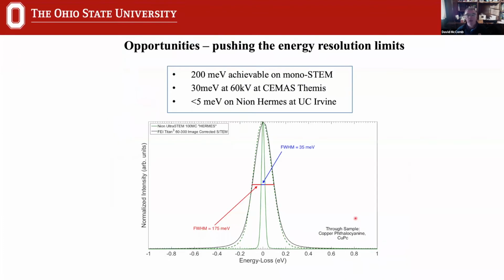Now, in fact, that has been significantly improved on in recent years. So with most monochromated systems, certainly an energy resolution of 200 millielectron volts is possible. On a new Themis operating at lower voltages at CEMAS, we can get 30 millielectron volts or better. And then in the Nion instruments, we've seen significant improvements over the last couple of years. And most recently, we've seen data reported that is less than 5 millielectron volts.